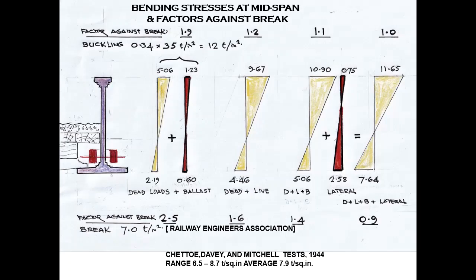We get a breaking or failure stress of 12 tons square inch. At the bottom flange, I've based the breaking stress on 7.0 ton a square inch, slightly higher than Hodgkinson, and it is the value used by the Railway Engineers Association in the 19th century. Compared with the value by Chetto, Davy and Mitchell tests of 1944 on existing cast iron bridges, which showed quite a range between 6.5 and 8.7 ton a square inch, averaging about 7.9. So my 7 ton a square inch is probably still a little bit conservative.